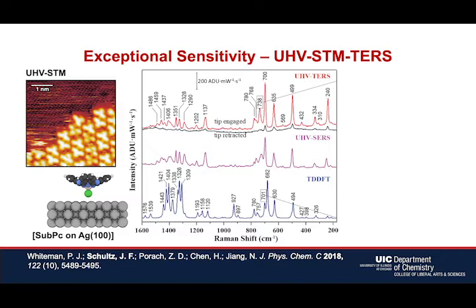As shown in the top left, it was possible to obtain high-resolution STM images of self-assembled boron subphthalocyanine chloride molecules with atomic resolution of the adjacent Ag(100) surface. The TERS spectrum, shown on the right, has an exceptional signal-to-noise ratio, permitting the clear identification of over 20 distinct